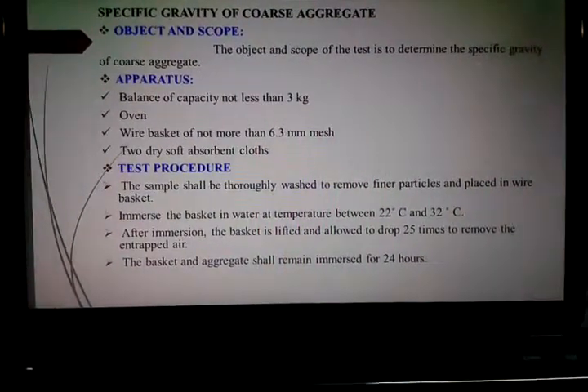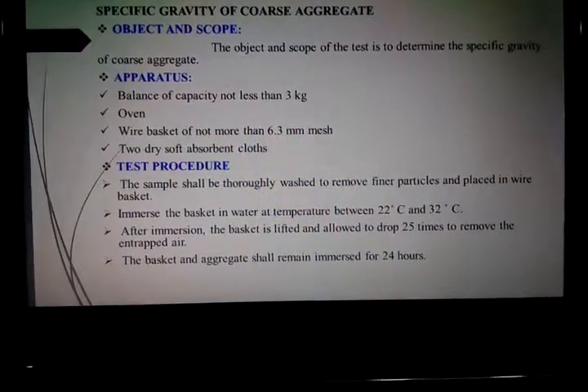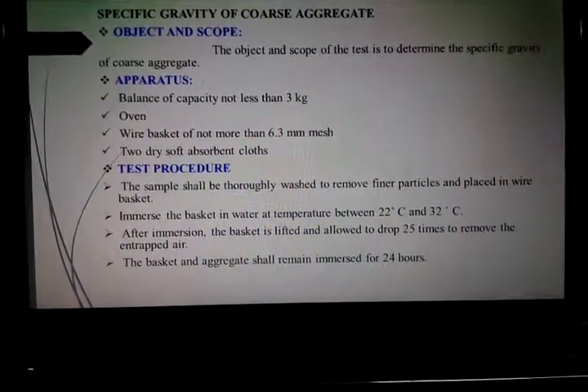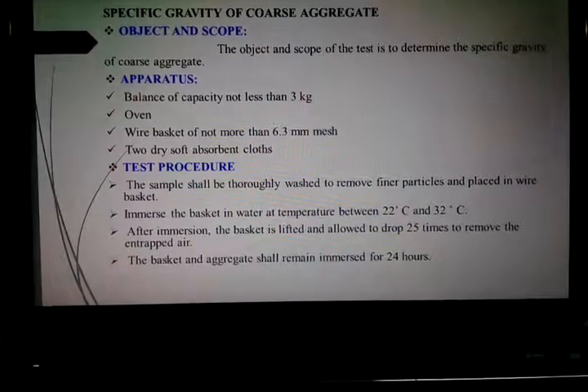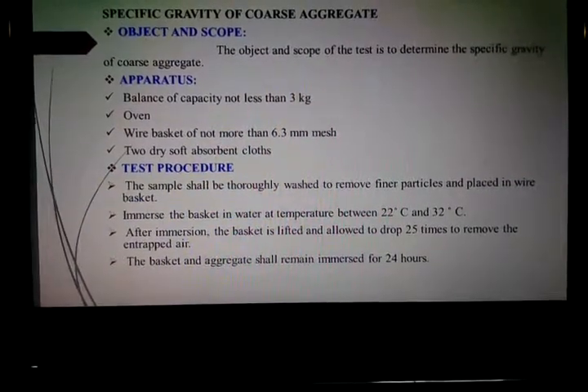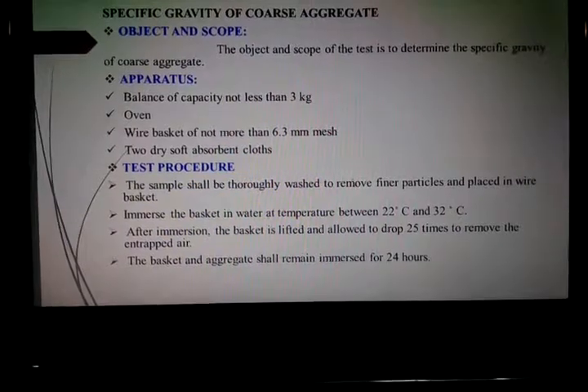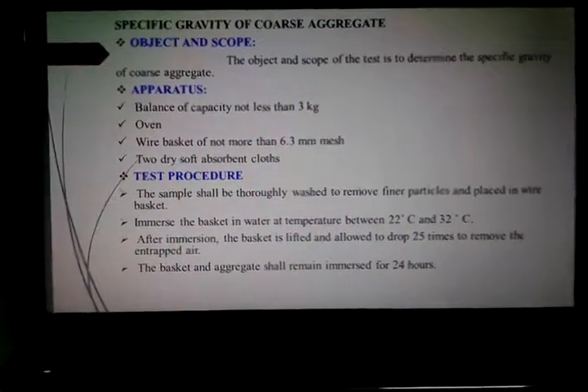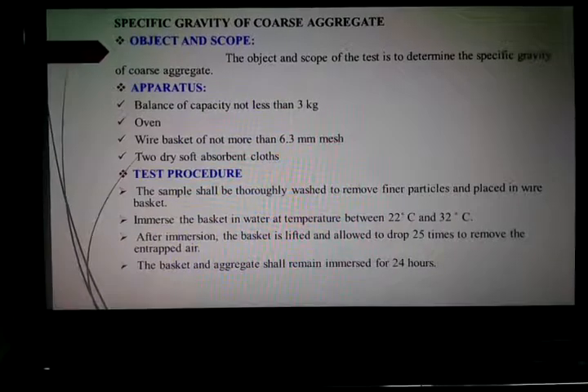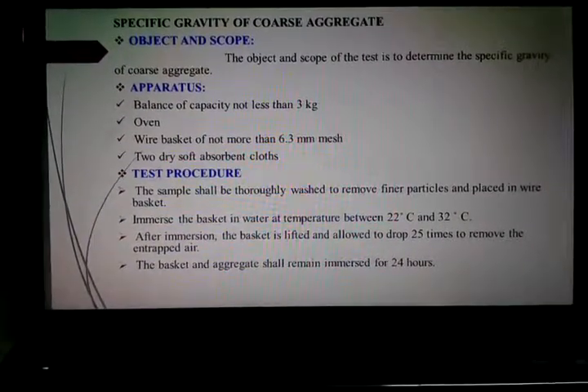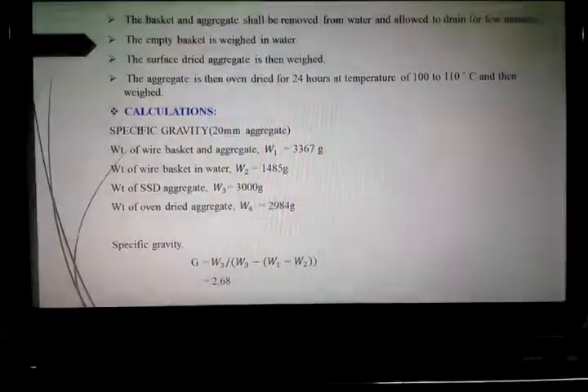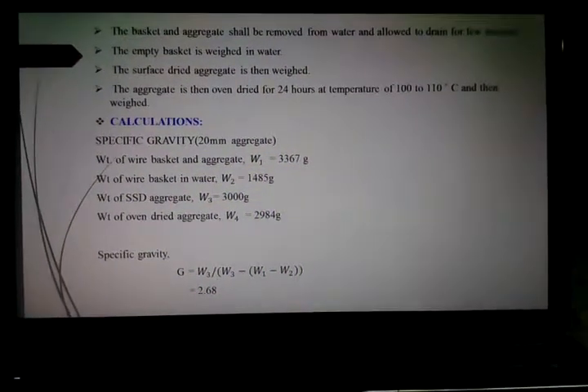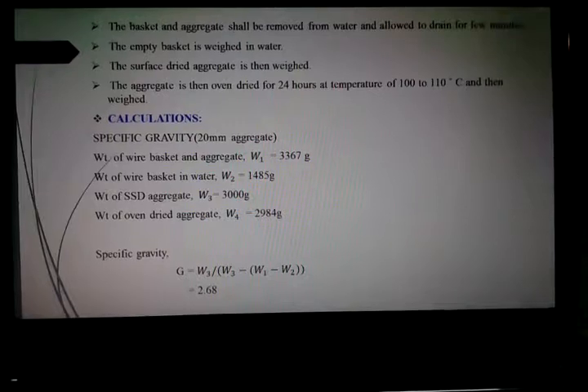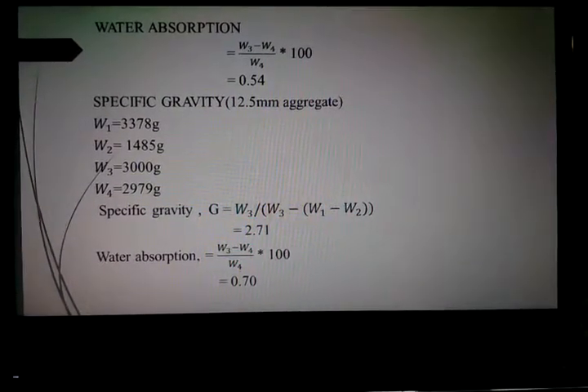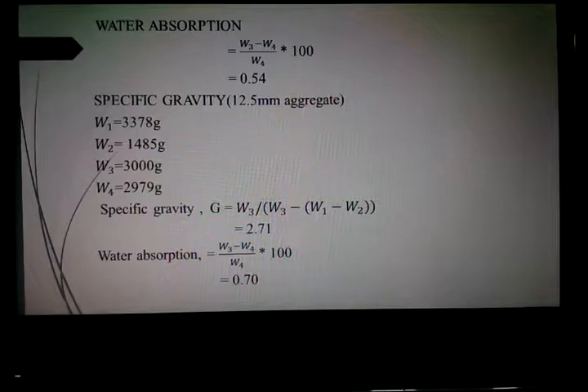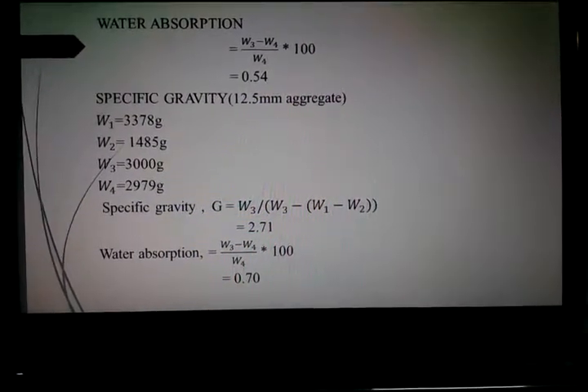Specific gravity of coarse aggregate. The objective is to determine the specific gravity of coarse aggregate 12.5 mm and 20 mm. The apparatus used are a balance of capacity not less than 3 kg, an oven, a wire basket of not more than 6.3 mm mesh, and 2 dry soft absorbent cloths. The test procedure conforms to IS code 2386. The calculations are done and the specific gravity of 20 mm aggregate was found to be 2.68 and the water absorption value was found to be 0.54. The specific gravity of 12.5 mm aggregate was found to be 2.71.